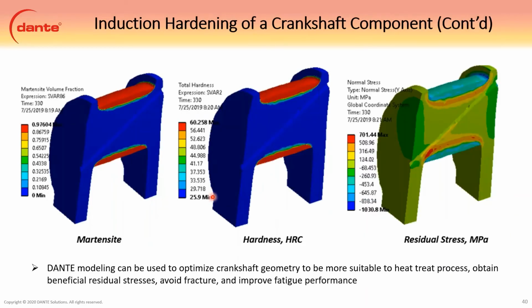So these are just still shots of martensite on the left, hardness in the middle, and our residual stress on the right. And what ended up happening was this oil hole got redesigned because it was too close to the bottom bearing surface down here. And you can see this tensile spike that you don't have up top. And it's all because this hole is closer to this bearing surface than to the top bearing surface. So it's very interesting.